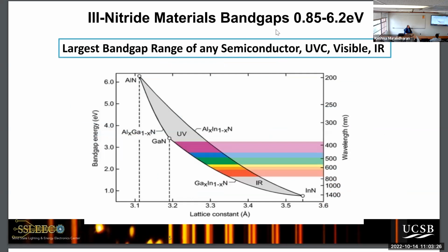Okay, so why this material system? Why did we settle on the gallium nitride, or what's called the III-nitride material system? This means column three. So that includes gallium, aluminum, boron, indium, and now scandium nitride. And I'm only showing you the AlGaN system. And the reason this material system is succeeding at these extreme energies, extreme wavelengths, is because it has the largest energy gap or band gap range of any semiconductor.